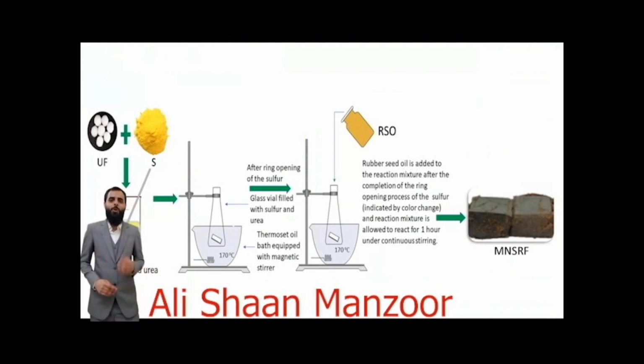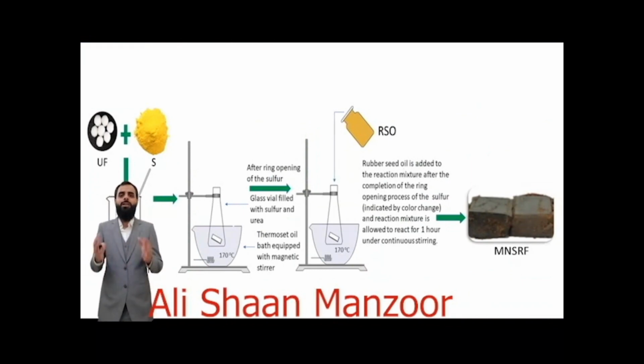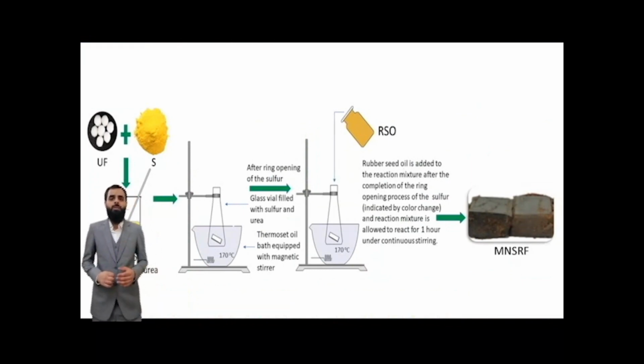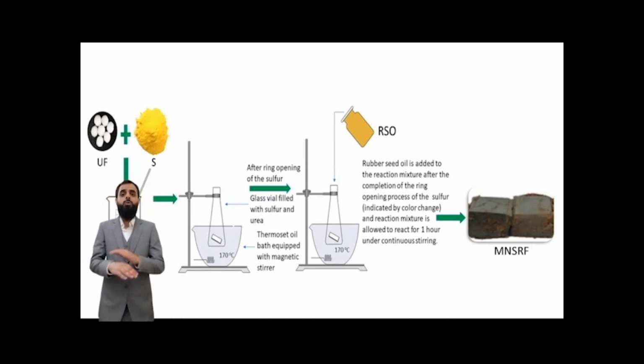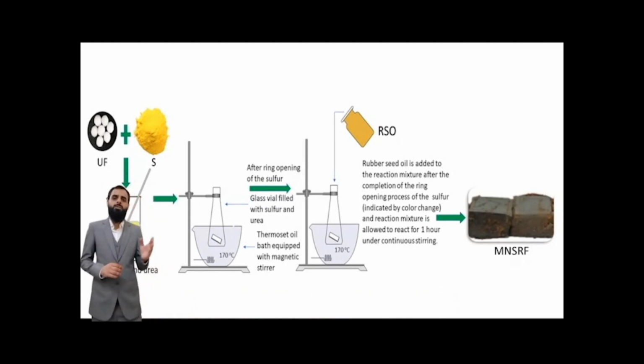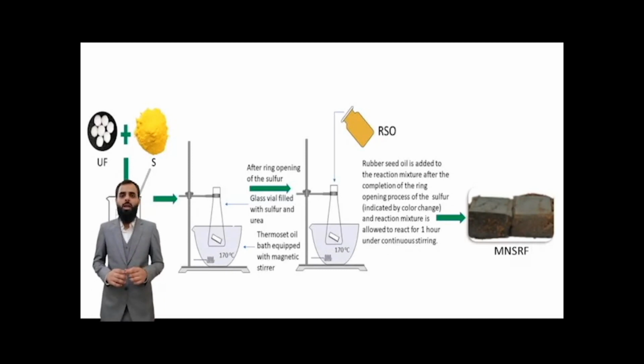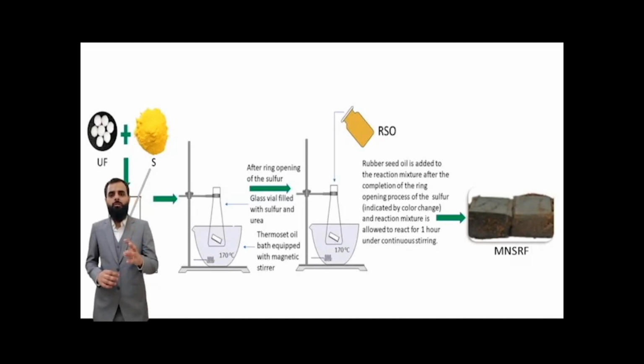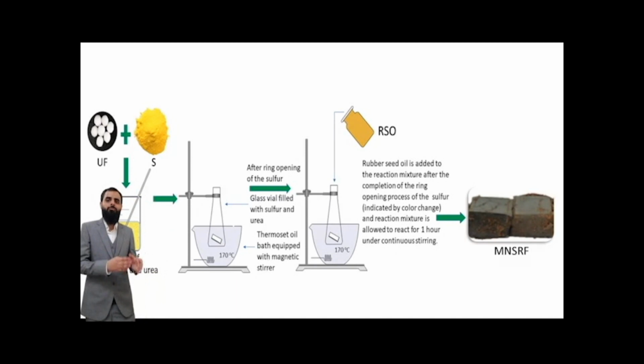Now let me explain to you how we actually produce this multi-nutrient slow-release fertilizer. We invented a methodology which does not involve the usage of any harmful solvent which pollutes the environment. We took a 60 ml glass vial. In that glass vial, we put 4 grams of sulfur and 8 grams of urea and placed that mixture inside the thermoset oil bath preheated at 170 degrees Celsius to melt the sulfur and urea.